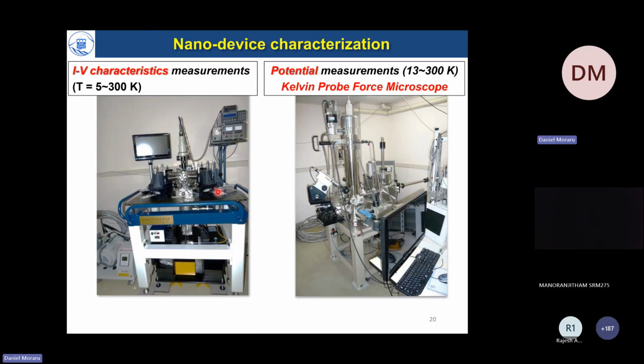So to do that, we utilize an equipment called IV prober, and that allows us to measure the IV characteristics in a wide range of temperatures. It's very stable mechanically because we have a lot of weights on the bottom here. In this metallic chamber, we can make a high vacuum with these pumps, and place our sample inside. Now, we can monitor it through this CCD camera on the screen, and we can control the temperature, from a helium compressor not seen in this image, to go down to even 5 Kelvin. Now, these manipulators here allow you to control very easily conductive needles that can connect you to a parameter analyzer, and you can measure the current.